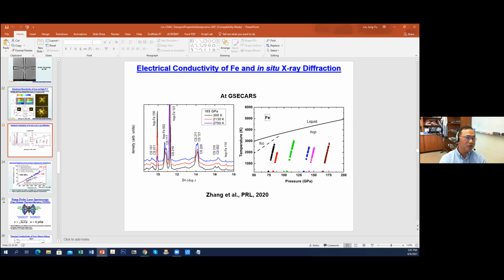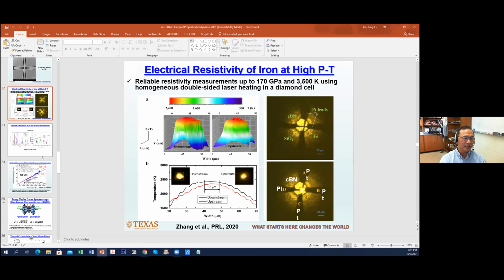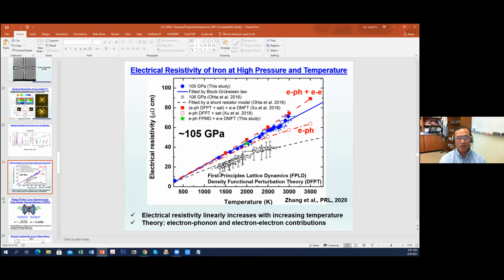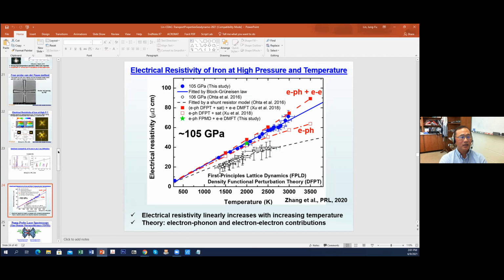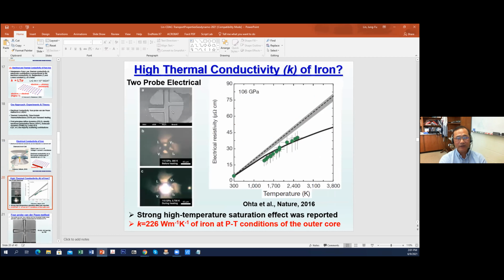And I think the major issue in Ohta's experiments, again, is really the sample geometry, that it's not really perfect. Like I mentioned earlier, if you have a piece of sample, let's say it's about this size, and you only heated a region of the sample, so that's a hot part and a cold part. What you are measuring is a combination of the hot and cold contributions. And that's why you are seeing this saturation effect here. If it's all hot, then it would go up more linearly for pure iron.